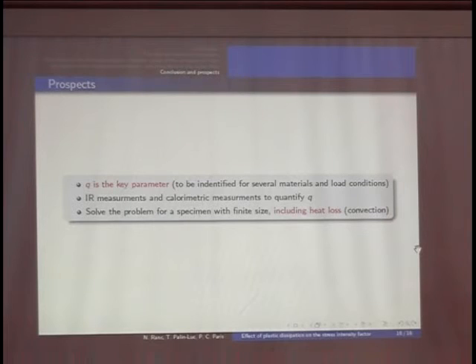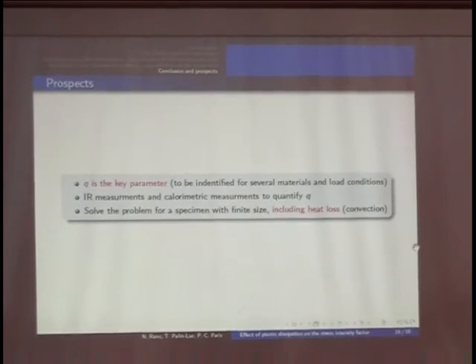Of course, here also in the model, which is simple, in fact, the important parameter is delta K, but in reality, maybe it's delta K effective. Yes. But in first approximation, to carry out the model, it's enough to consider delta K. But I think we have to go deeper in experiments with very, I will say, precise measurement of delta K and delta K effective to be close to reality. We are starting experiments only six months ago, so it's the beginning.